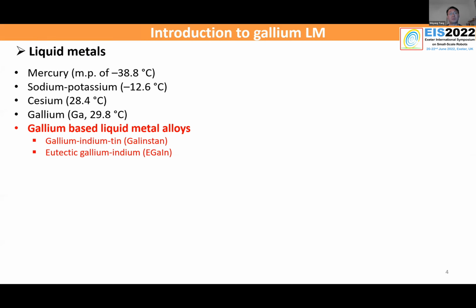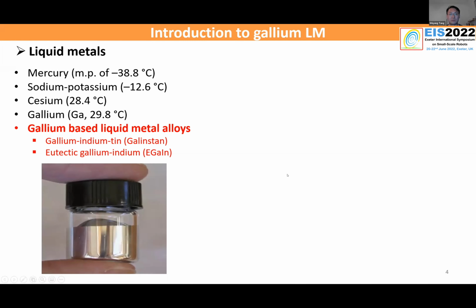Another two metals which have melting points close to room temperature are cesium and gallium. They have melting points of approximately 29 degrees Celsius, but cesium is also extremely reactive. The material we're currently working with is called gallium-based liquid metal alloys. The two most widely used alloys are, first, galinstan, which is an alloy of gallium, indium, and tin, and secondly, eutectic gallium-indium alloy. This type of liquid metal looks very similar to mercury, with a silvery metallic color, but it also forms an oxide layer, which I'll talk about later.